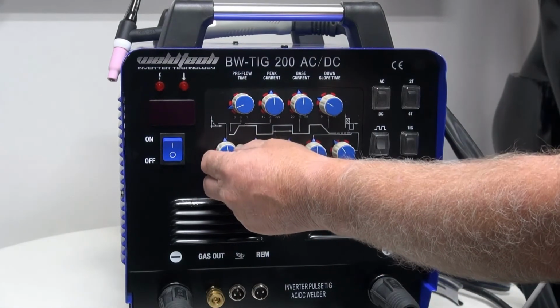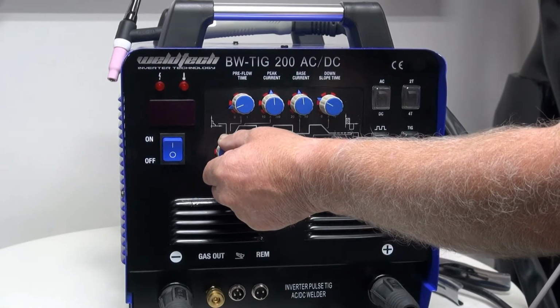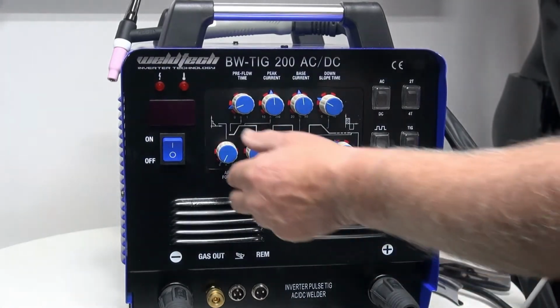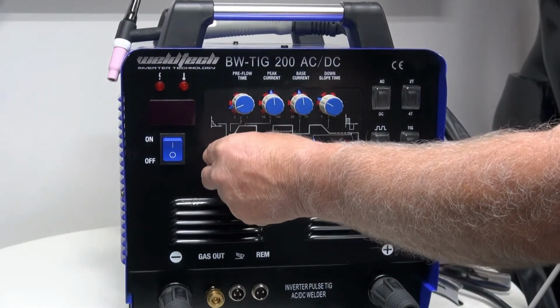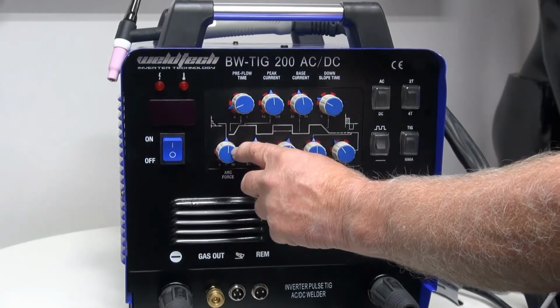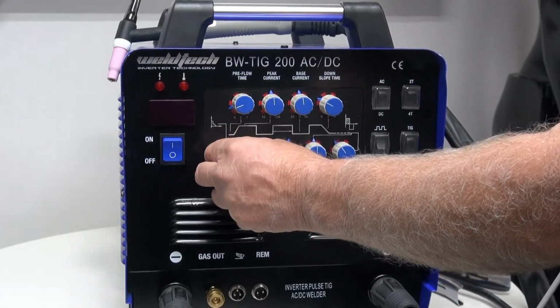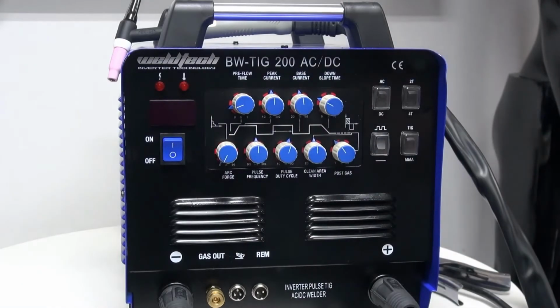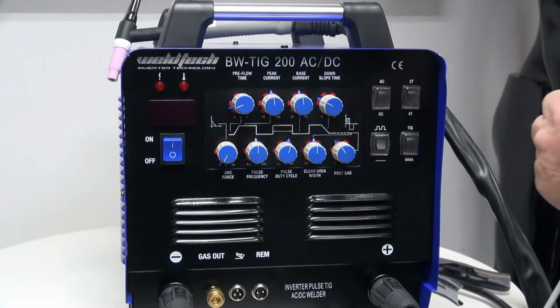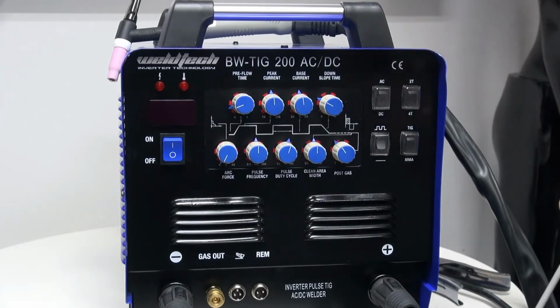Now there is a trick that I have learnt with these types of machines over the years: when you're doing TIG welding, this knob should be set at zero. When you're arc welding, I like 50% or something like that. But I will say it again, when you're TIG welding, you put it on to zero. If you don't, it means that when you're TIG welding, the tungsten will reach out and grab more energy at the start, possibly burning a hole through your job.